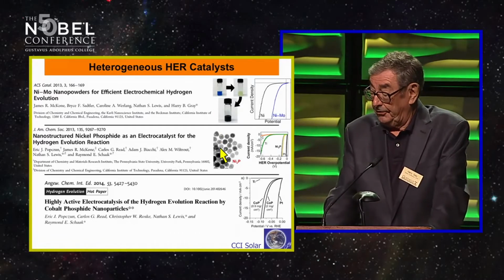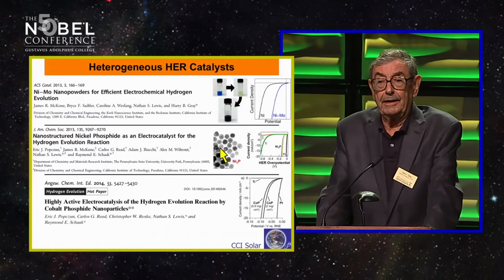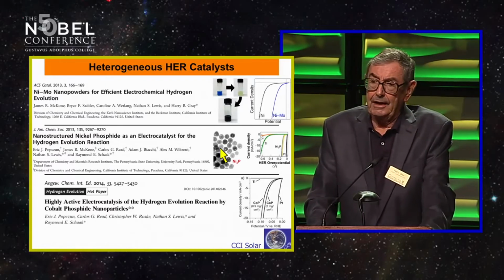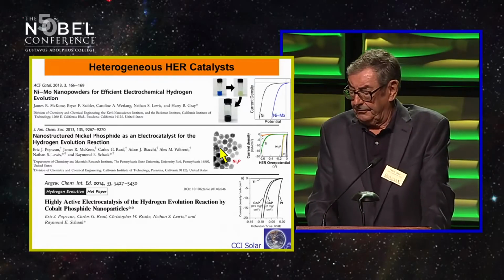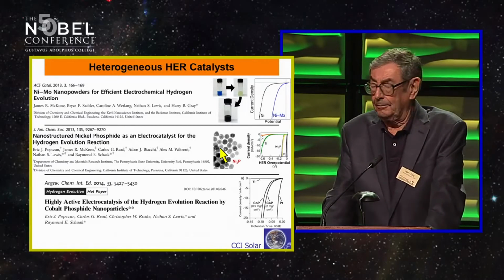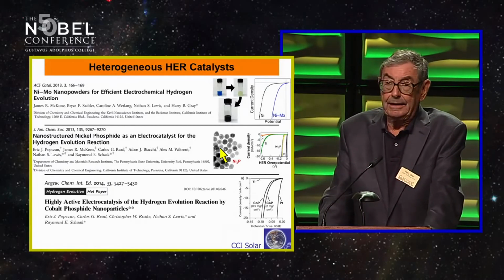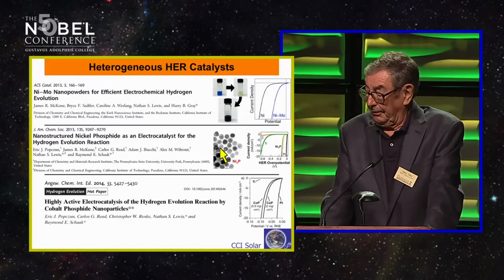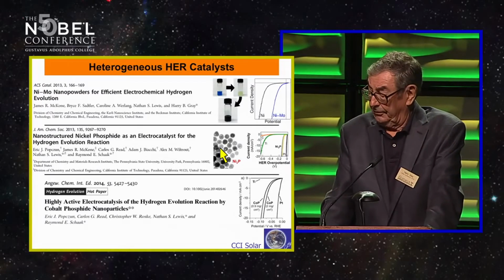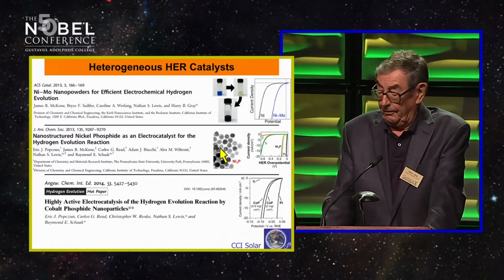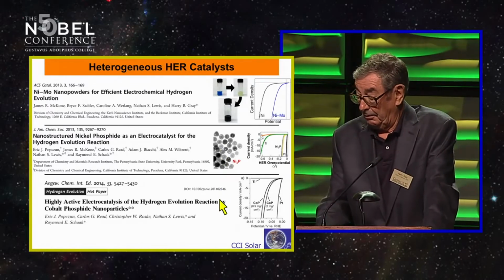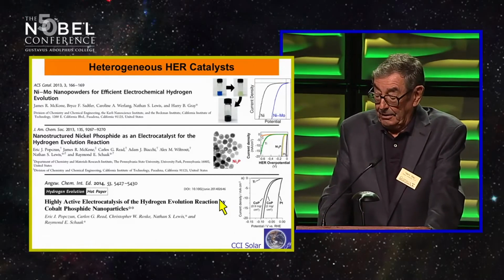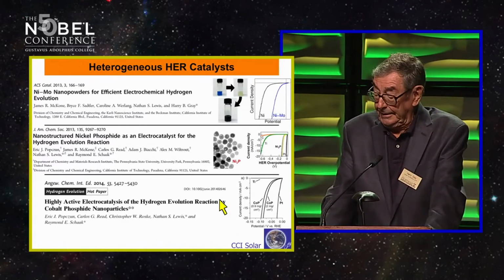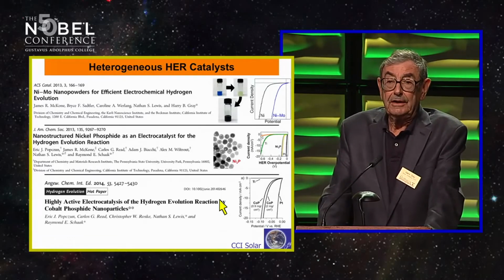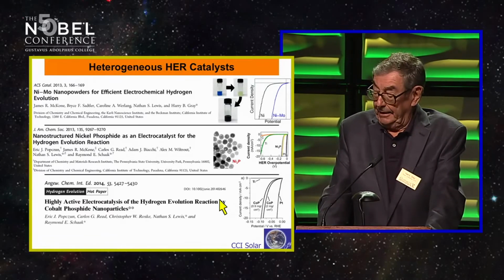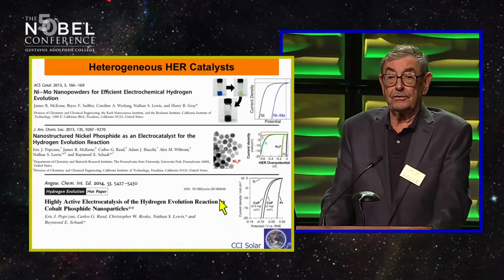At Penn State, Raymond Schaak has made a nickel phosphide by pyrolyzing an organophosphorus compound in the presence of simple nickel salts at high temperatures and getting this black nickel phosphide nanomaterials that you can drop cast on electrodes to get very, very active hydrogen evolving systems. And finally, one that we're working on at Caltech, an analogous cobalt phosphorus compound, black compound that operates essentially as well as platinum and under many, many conditions of acid and base.